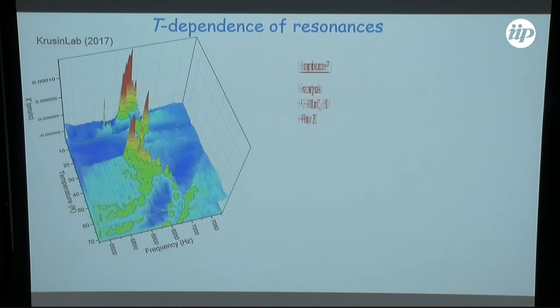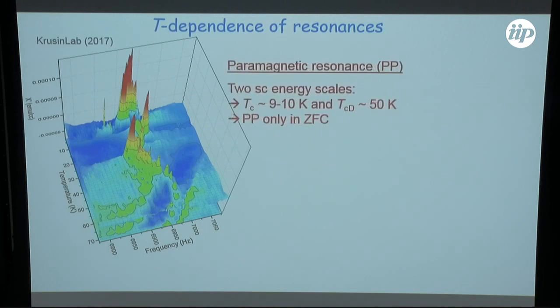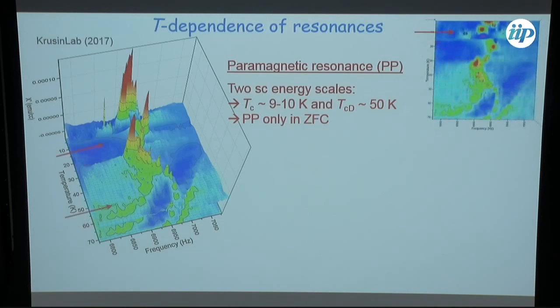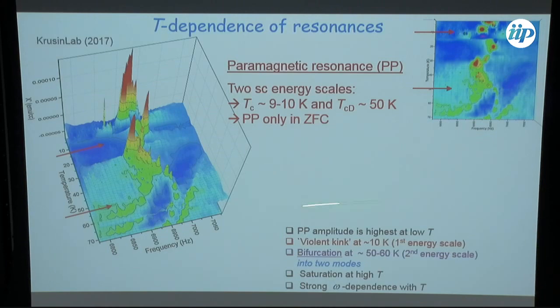and disappears. So the key here is that in these resonances, at high fields, we actually can reproduce these 2 temperature scales related to the original superconductivity. And so the question is what it is. And in fact, you can see here on this projection that it's exactly at the same temperature scales. Now, there is a saturation at high temperatures. There is a highest amplitude at low temperatures. And there is strong frequency dependence with temperature.